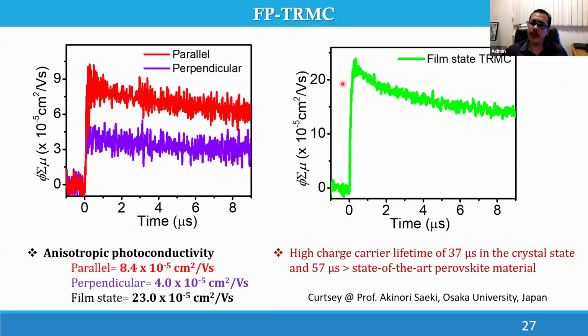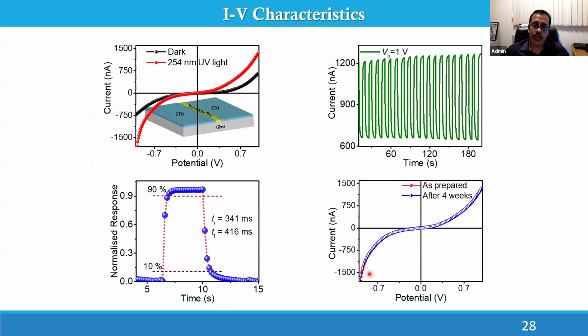And the films are showing much better conductivity and very high carrier lifetime of 37 microsecond in the crystal, and 57 microsecond in the film state, that is state of the art or the record at that time. And we did detailed photo detector analysis with these materials, and our material was giving very beautiful photoconductivity signal at 254 nanometer. That is a deep UV range, and with a beautiful rise and fall time.